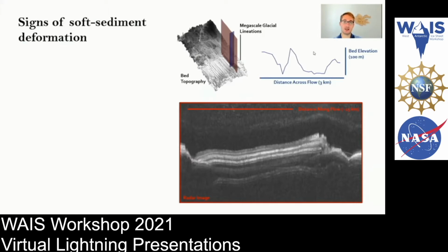So in 2009 and 2010, high resolution radar imagery were collected at 2 locations in West Antarctica at Thwaites Glacier. Together with swath radar processing techniques allowed us to produce really fine resolution DEMs of the glacier substrate. And what we saw in those areas were really interesting indicators of soft sediment deformation. These lineations within the substrate oriented in the same direction as ice flow.